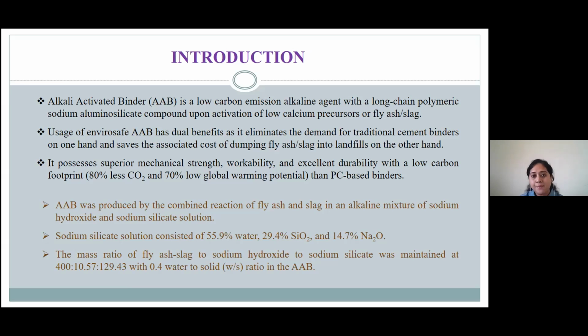Now, AAB, or alkali activated binder as we call it, is prepared by blending aluminosilicate precursors, that is, we have used fly ash and slag in certain ratios, with an alkaline solution consisting of sodium silicate and sodium hydroxide. We have chosen 3 water to solids ratios, 0.3, 0.4, and 0.5. If we use a water to solids ratio less than 0.3, workability becomes an issue, and if we increase it beyond 0.5, it becomes too liquid.